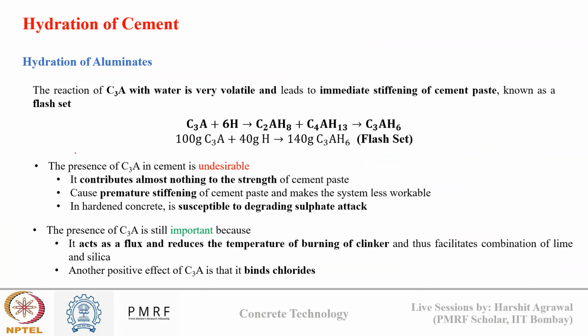Now, in case of hydration of aluminates, we have just studied that C3A is very reactive due to its lack of polymerization and open cubic structure. So the reaction of C3A with water is very volatile in nature because it is highly reactive and it leads to immediate stiffening of cement paste. When we add water to cement, the first composition of cement which reacts with water is the C3A, and it causes stiffening. It will make the cement paste very stiff, which is also known as flash setting.